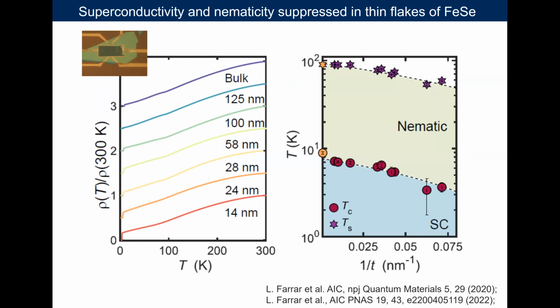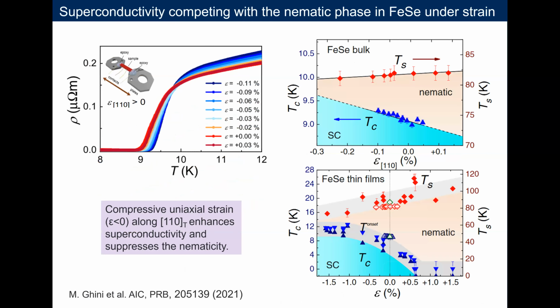Iron selenium is also great because you can exfoliate the system. You have van der Waals layers. And here we created devices by flaking our crystals into thinner and thinner layers. And in a similar way, like we saw with the copper substitution, both the nematic phase and the superconducting phases were suppressed, which is different from when you grow the material in a monolayer.